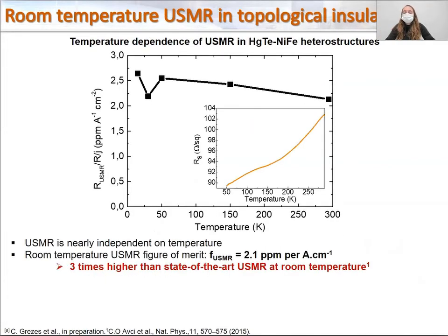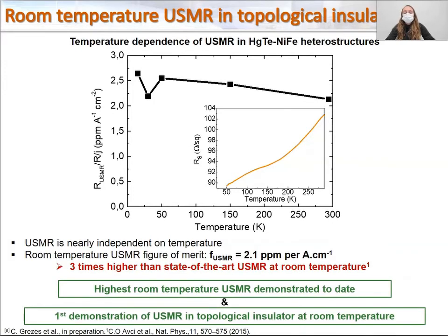Given the high mobility in HgTe up to room temperature, we repeated the same USMR measurement at different temperatures. The experimental result at room temperature shows comparable USMR efficiency, with nearly temperature-independent USMR. Importantly, we demonstrate the highest USMR efficiency to date at room temperature, and we made the first demonstration of USMR up to room temperature in a topological insulator.